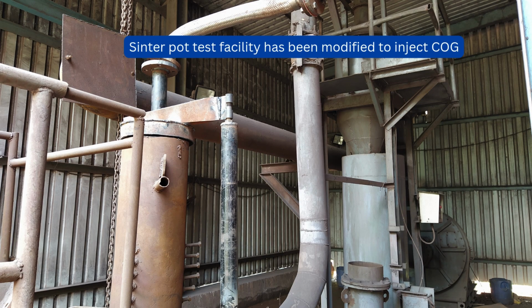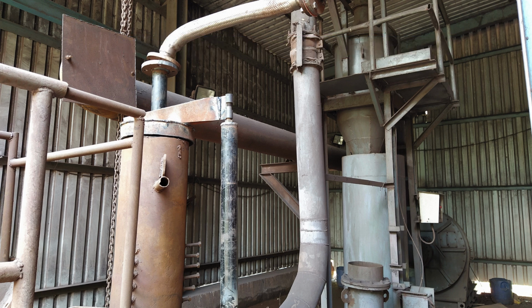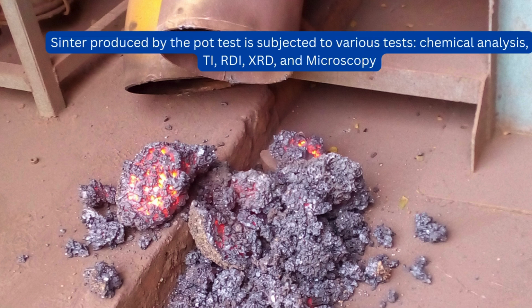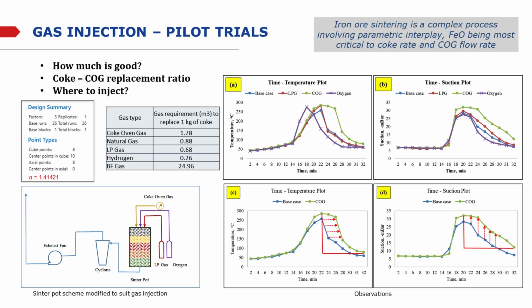The pilot trials began in 2019 using Sinterpot facility. It did not have arrangements to inject gases, so we introduced gas injection system and conducted trials. The product sinter was dense, had higher strength, and better elevated temperature properties. Due to parametric interplay, which is inherent to sintering process, the alpha in the design of experiment showed 1.4.